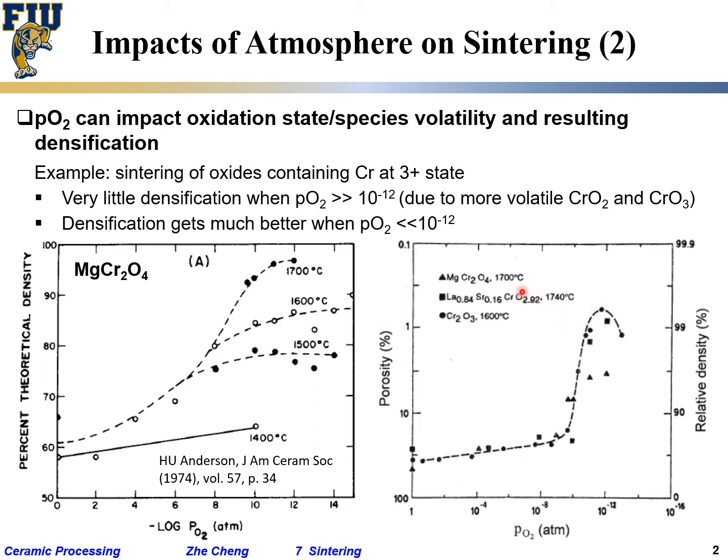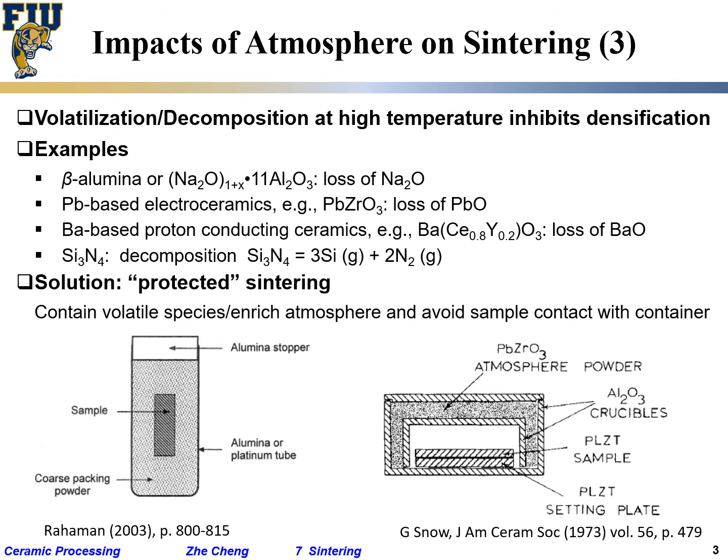You still have to heat up to 1700, roughly in that range. But be careful with your atmosphere. And you achieve that atmosphere with certain apparatus, like a tube furnace or a specially designed box furnace, but not with your typical open muffle or box furnace. Make sense? That gives you an idea, okay.